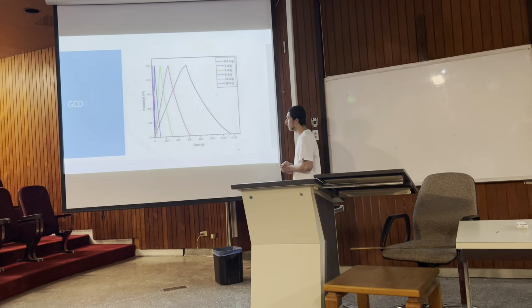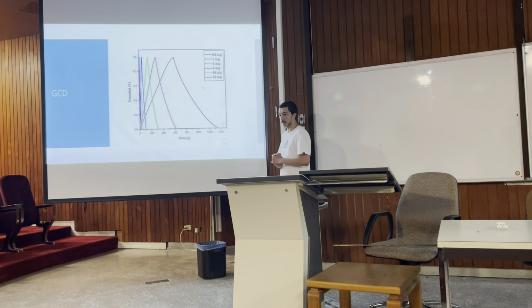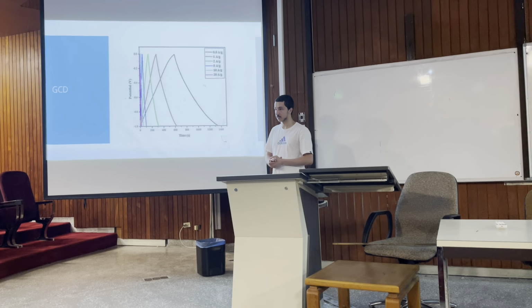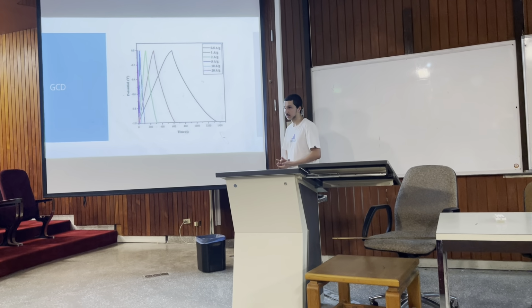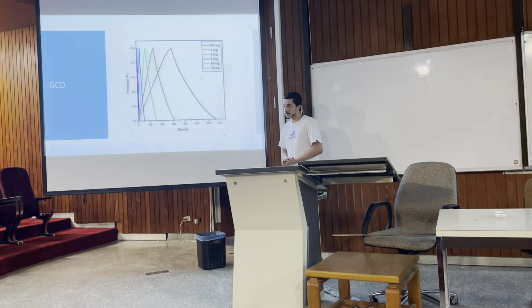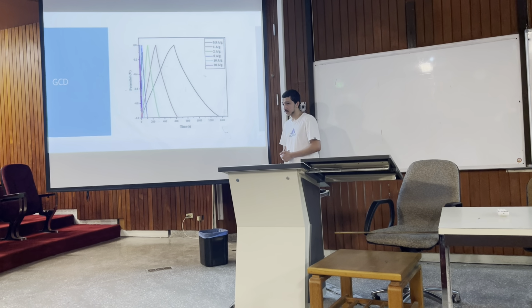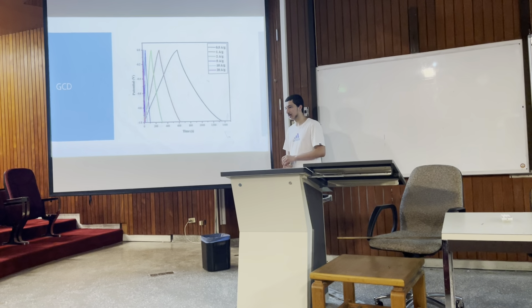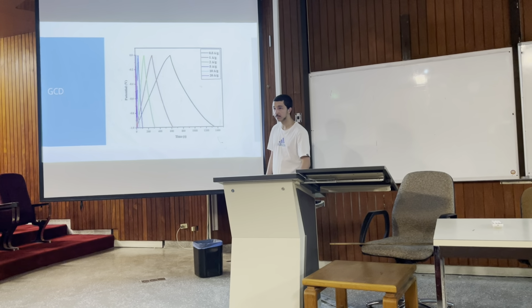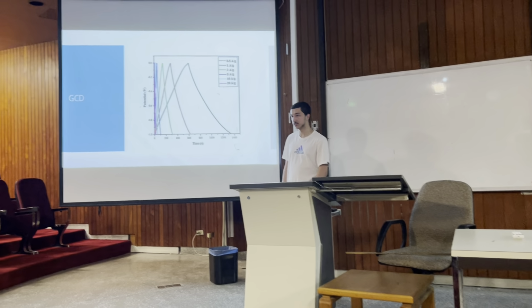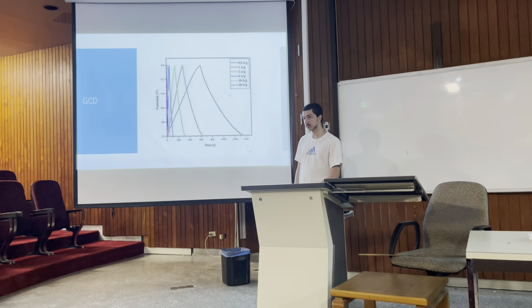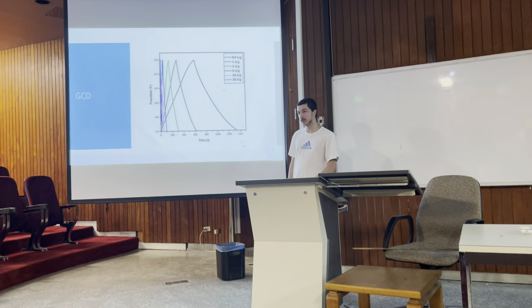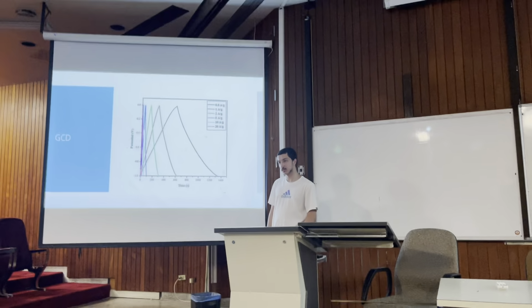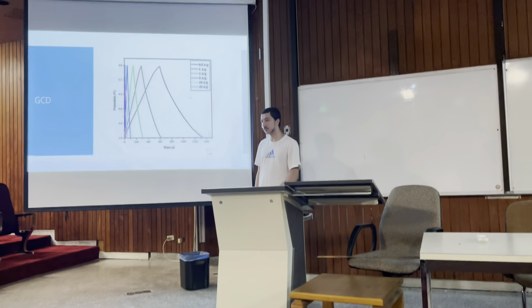So the specific capacitance, what we call it, that's why he says per gram. Normally it's farad, but we say how many farad per gram. And what is the dielectric in between? It's the electrolyte. So this electrolyte actually is polarized. That's why he says in the EDLC, if you put a positive charge on one electrode, the negative side of the electrolyte comes closer to it, and there is charge separation.